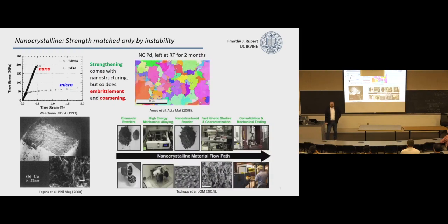This also comes up in the ability of having a stable microstructure. So this is another example from what was once nanocrystalline palladium, a similar material to this. These people deposited these nanocrystalline films. They were getting the properties they wanted. Great, they were celebrating. But if you just leave this material at room temperature for 2 months, you go back and look at the microstructure, you now find that these crystals are much, much bigger, tens of microns. It's no longer nanocrystalline. You totally lost that thing you were after, right?